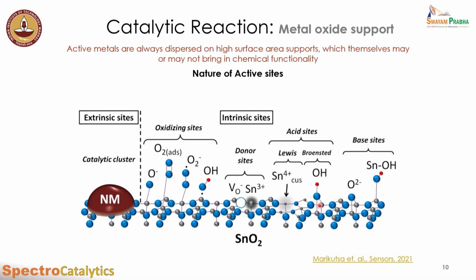These oxide structures are not ideal in reality. They have many different kinds of terminal sites. For example, there can be vacant sites where oxygen is not present. There can be coordinatively unsaturated sites where the tin atom is not present. There can be some oxygen which are not bound to the tin so strongly that this oxygen can participate in the reaction. There can be hydroxyl groups, which are nothing but OH ending species on the surface, and they can participate.